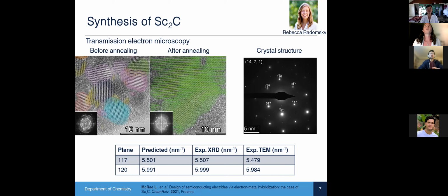And so we are now trying arc melting with titanium, which will suck the oxygen out of the arc melting chamber. And then we're also going to try annealing with titanium in the tube in order to make sure that we're purging the entire environment of oxygen to favor this thermodynamic phase. That way, any of the impurities will hopefully be taken out. So that's our next step in trying to improve the purity of the sample and getting the conductivity a little bit closer to what we're expecting from computation.